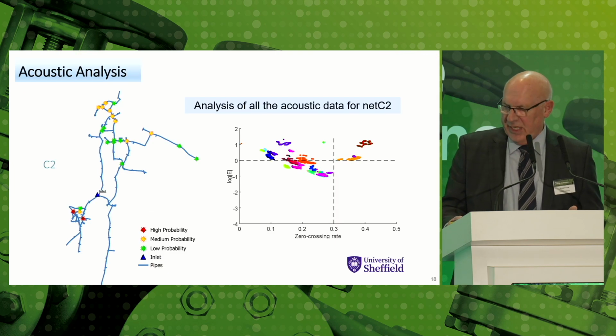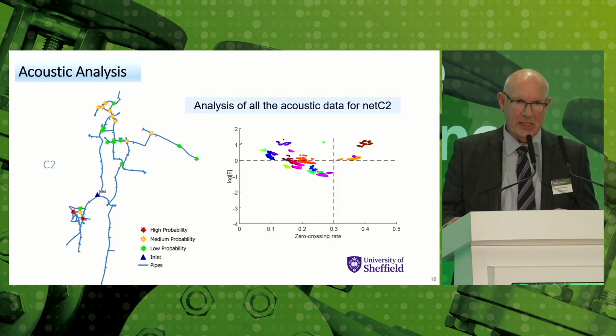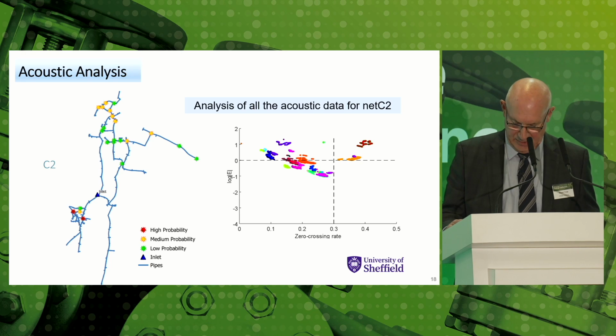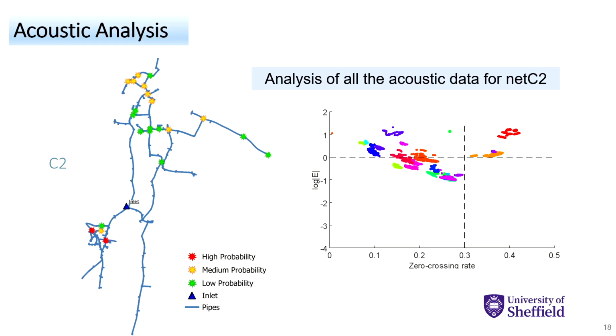They've then developed new techniques on the acoustics. We've got a PhD student working on the project full-time. We're not just relying on the alarms from the loggers, we're actually recording and analysing the acoustic data from the loggers. I can't go into the detail, but where we see these red dots in the top right of these graphs, that is indicating a leak at that point in the network, which isn't being picked up on the alarms from the loggers.